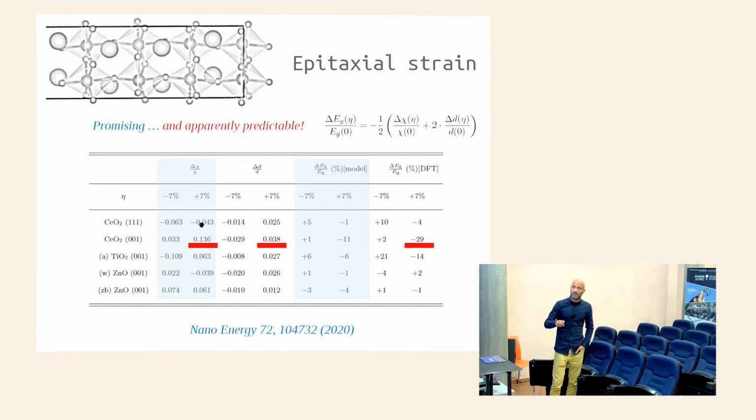Another important thing to mention is that the changes in the structural parameters are quite systematic: you always have these positives, these negatives. On the other hand, for the electric properties, that's not the case. It is very much material dependent and very much dependent on the actual strain. This non-systematicity, together with the regular pattern of the other term, gives you at the end of the day what up to this point was not systematic, but that now we think we can understand better, the trend.